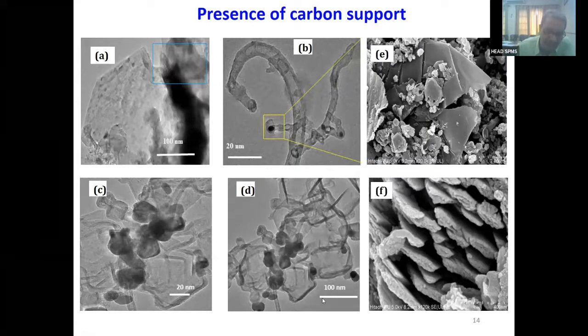A similar phenomenon you can see over here: this thin layer is rolling out, and this thin layer is converted into a very fine carbon nanotube. You can see they are going to form. So these are the structural features which we have observed in the material synthesized at different temperatures, so that we can predict the actual mechanism of what is going to occur inside the material.